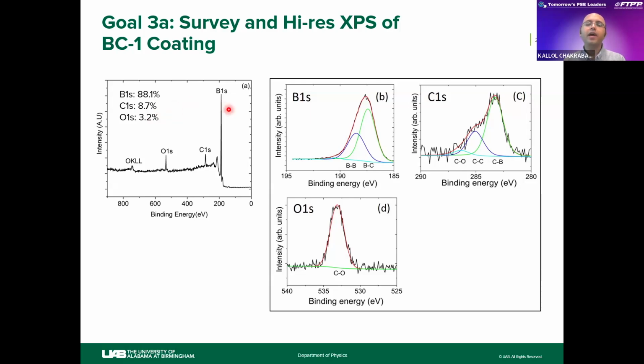Next, we did high resolution XPS to confirm if we have some boron carbide peak in the spectra. As you can see, we see the BC peak in the high resolution B1s, and you can see the C-B and C-C peaks as well in the high resolution C1s peak. So we can definitely say that our boron is bonded to the carbon according to the high resolution XPS.